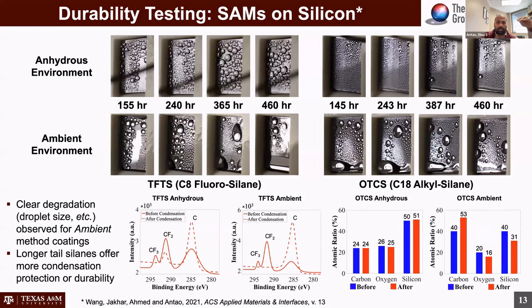We had to stop the experiments at 460 hours because we wanted to actually see what is happening with the surfaces that failed. And my student wanted to graduate, so a lot of stopping experiments is to not obtain binary data, as well as have data available in a time frame that's conducive to a 3 or 4 year PhD degree. But if you look at the XPS data that we obtained before and after the testing process,